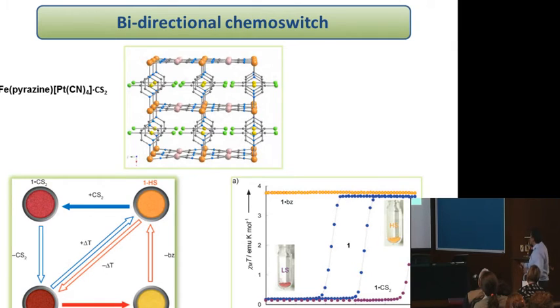And you also have the reversible process. If you are here in the high spin state, and then you introduce CS2 molecules into the system, you will switch back from the orange to the red color. So we have demonstrated this bidirectional chemoswitch.